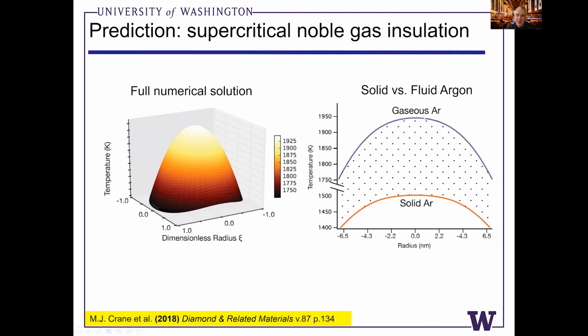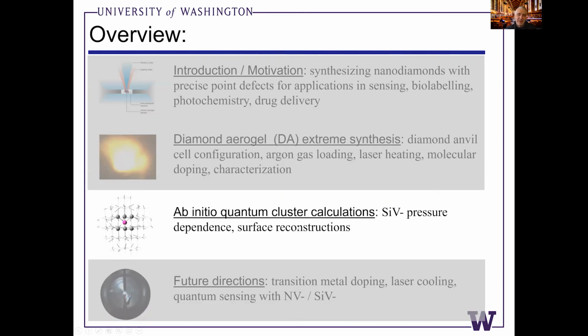So you can easily explain this temperature jump in terms of just a change in the thermal conductivity of the surroundings of the aerogel. And so our hypothesis is that these gaseous argon atoms are very mobile. They can diffuse very readily and potentially infiltrate the amorphous carbon before it crystallizes. And some of these argon atoms get trapped in the lattice, but we don't have a clear picture at the moment. Are these split vacancies? We have some EDAX mapping that I'll share that clearly shows there might be some pockets of argon too, maybe bubbles of argon trapped in these materials, maybe at grain boundaries.